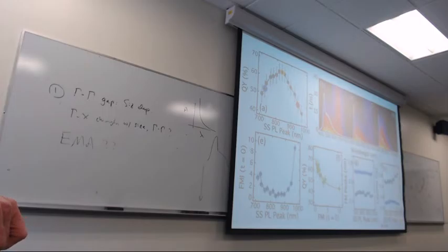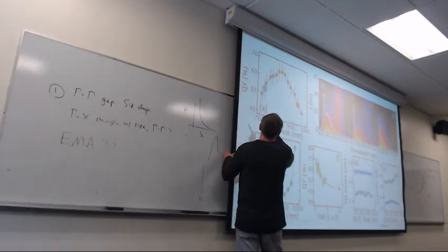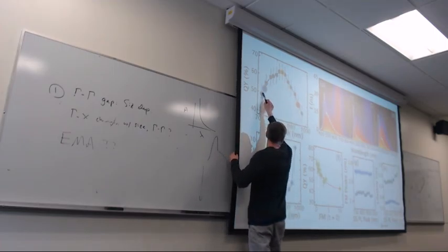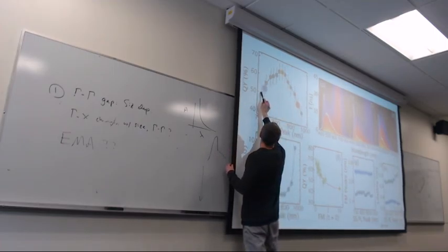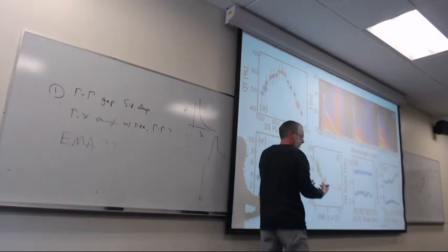And if it's gamma, it's the intensity that changes, not its position. The intensity might change just because there is more surface, more contribution of such states. That's how I would interpret it, because it gets big as you get smaller, which just means the surface is becoming more important. And this peak gets big as you go to the higher fractions, which are going to have more defects in them.